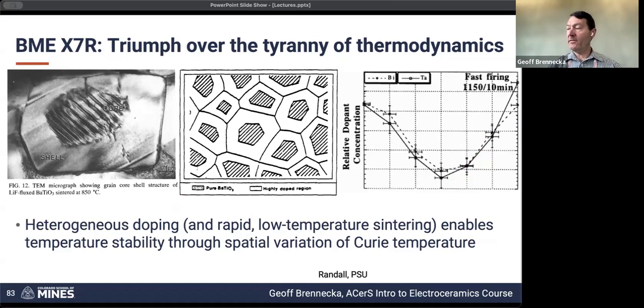You notice something else on here that says fast firing. In order for this to work, you need to balance the diffusion coefficients and the diffusion rates of all these different dopants so that you don't sinter long enough that everything becomes homogeneous, but you do sinter long enough that everything becomes dense. And so it's a race between getting the dopant materials to diffuse where you want them, and the densification to happen without everything being completely homogeneous and losing the advantages of the core shell structure. So this is one of the early stages of going to a fast firing sort of approach.